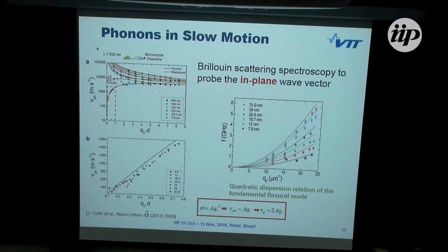And the whole set of measurements with different modes looks like this, but when one focuses on this lowest flexural mode, then one can see that the dependence is actually linear. This is the normalized wave vector, so multiplied by the thickness. And these numbers really show that the phonon speed goes down. So this is phase velocity, but this also applies to group velocity. So phonons move slowly.